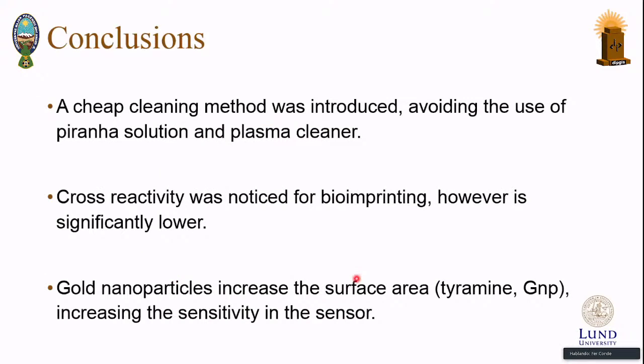As conclusions, the first conclusion that I have is that a cheap cleaning method was introduced, avoiding the use of piranha solution and the plasma cleaner. We have seen in bioimprinting that cross-reactivity was noticed, however, this is significantly lower for the interactions. Gold nanoparticles have been seen to increase the surface area in the case of tyramine and gold nanoparticles, increasing the sensitivity in the sensor.